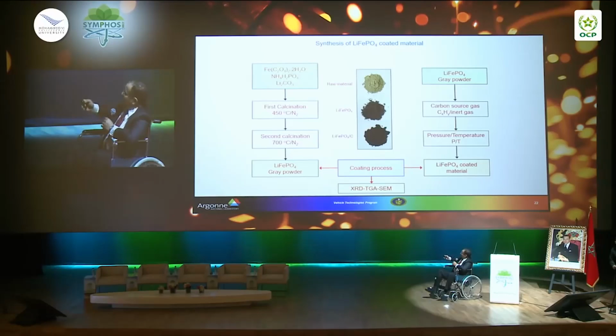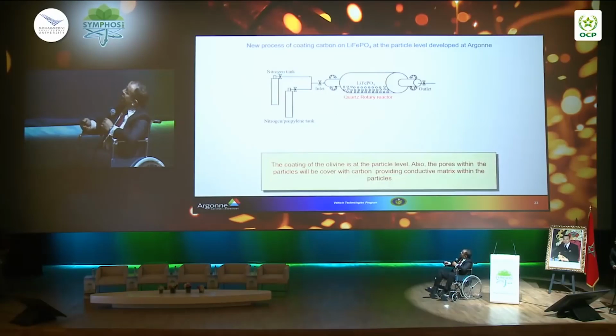I'm going to show you how to do the carbon coating. A lot of people use polymers or carbon mixing. Here is a much cleverer way, which is using propylene or toluene, because it's a gas. Gas goes everywhere, so you basically end up having contact with all the particles, not just surface contact as if you do a normal mix. And you can do that easily at very low temperature. You crack propylene and you form carbon at the surface of this nanomaterial.